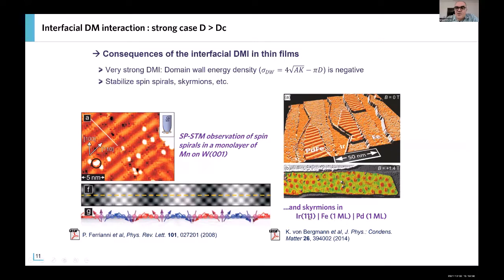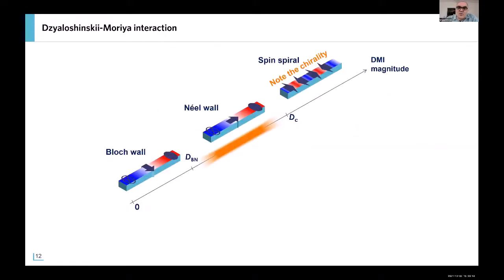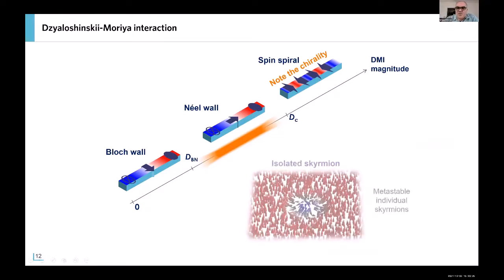And rapidly after, by applying a very large magnetic field and at low temperature, they could even get some system where this spin spiral can be transformed into a Skyrmion lattice phase. So this is for the case of very strong Dzyaloshinskii-Moriya interaction, above this threshold value. But if we want to have isolated Skyrmions, we are more interested in this range of Dzyaloshinskii-Moriya interaction that is below this threshold value for stabilization of lattices.